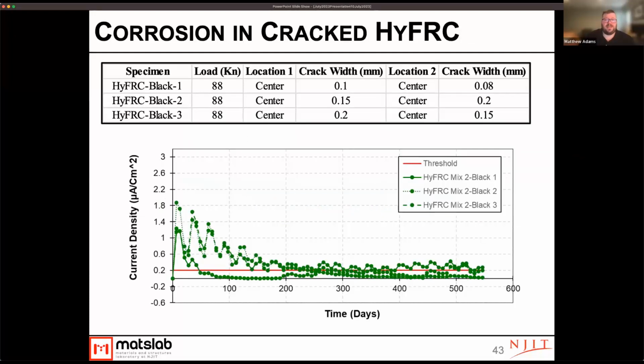What we see here is that in particular, we had one of the three specimens that had a higher corrosion density than the other two. And this was the one with the largest crack in it as well. We also see some higher corrosion density early on. This is an artifact of the test method. As the system saturates with water over time, at that early age, you tend to see some higher corrosion density. But what we're really concerned with is the long-term corrosion density.